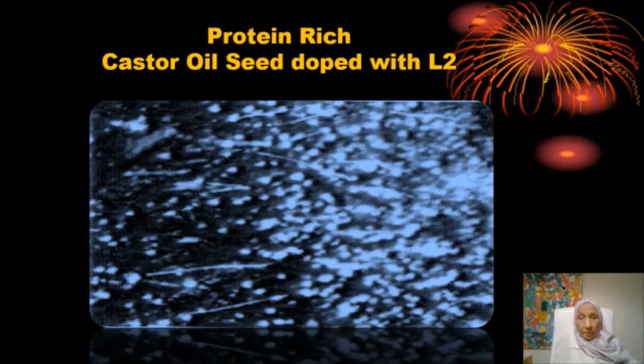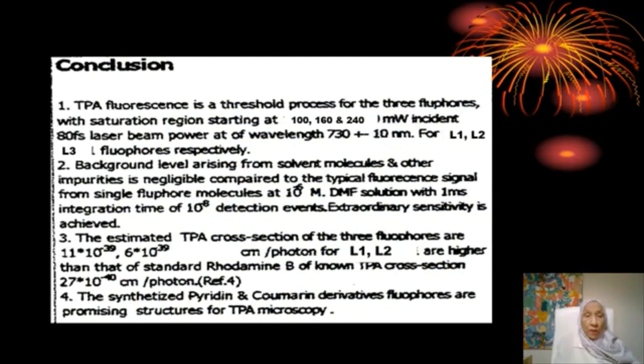Conclusion, we have two photon absorption processes, a threshold process for the three fluorophores which we prepared, with saturation ranging region starting at 100, 160, and 240 milliwatt incident, 80 femtosecond laser of wavelength 730 for the L1, L2 and L3 fluorophores respectively. Background level rises from solvent molecules and other impurities is negligible compared to the typical fluorescence signal